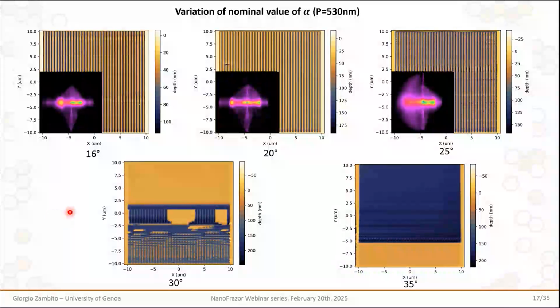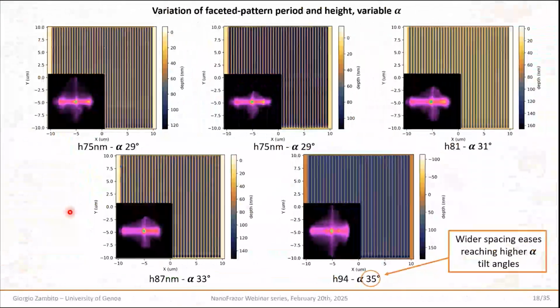But the point is that we have to take into account that thermal scanning probe lithography, of course, relies on the use of a hot nanoprobe, which has a conical shape and hence has some intrinsic limitations. And we can ease the patterning process, for example, by allowing easier geometries, and for example, allowing wider spacing and wider periodicities. And by appropriate variation of these geometry parameters, we were able to achieve steeper facets up to 35 or so degrees.